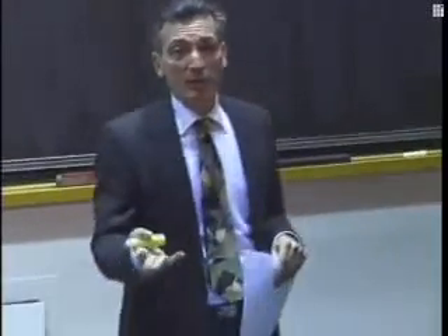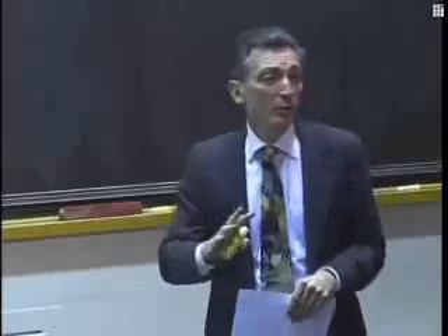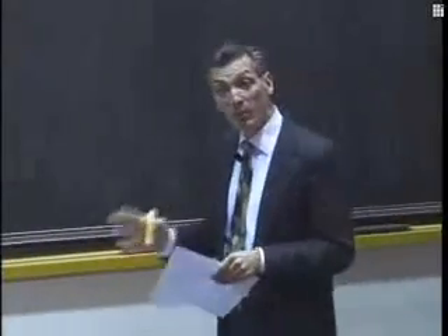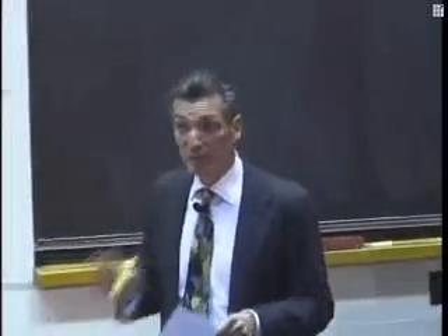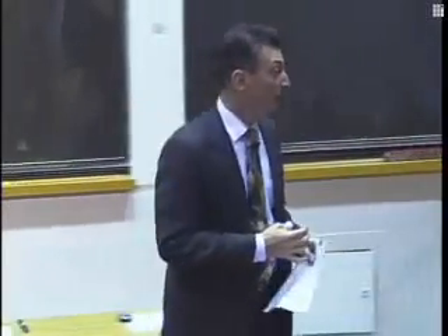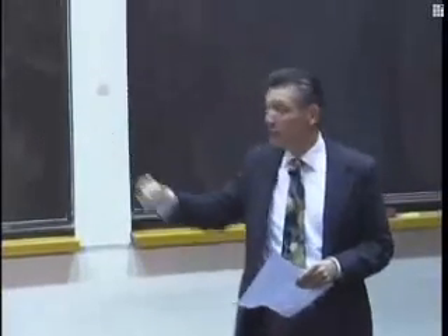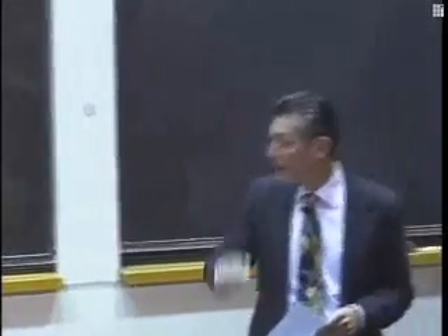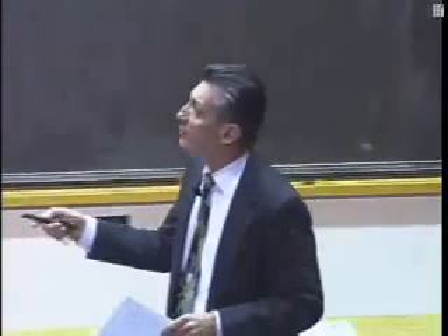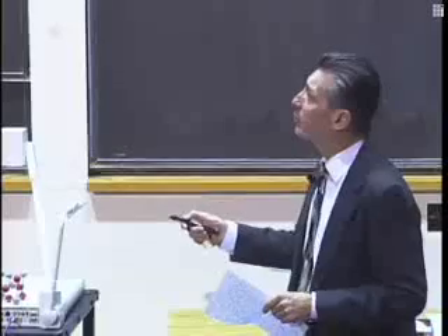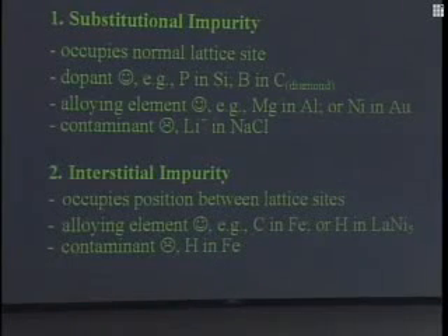If we're going to put hydrogen on cars, if at some point fuel cells become practical, what is going to be the mode of storing hydrogen? Do we want compressed hydrogen? We're going to have all sorts of protection in the case of a collision. Well, this might be a safer way of putting hydrogen on the vehicle. So interstitial packing is advantageous in this case. But if we get our wires crossed and instead of putting hydrogen in lanthanum nickel 5, we put hydrogen in iron, that leads to deleterious effects. Hydrogen in iron embrittles iron, and it loses its ductility, becomes very brittle, and can fail prematurely.